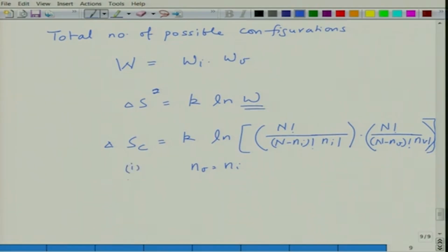so first condition is n sigma is equal to n i, then second approximation is Stirling approximation for a large n, that is ln of n factorial is equal to n ln n minus n. For large numbers, we make this approximation. If you apply this, you can do the maths yourself, delta SC is equal to 2 k, small k is the Boltzmann constant, n ln n minus n minus n ln minus small n ln n,